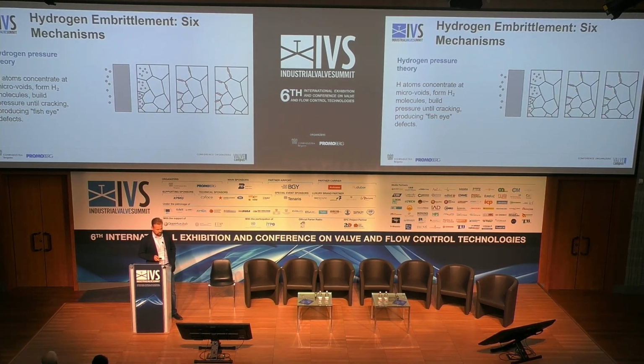So, going straight into it, the biggest problem that we have probably heard the most about is hydrogen embrittlement. Okay, so the sometimes reversible, sometimes irreversible loss of mechanical structure of metal. There are 6 different possible mechanisms. Some of them were actually observed, some of them are just theories, and the math is there, so it just works because the calculations are on point. One of the easiest and oldest theories is that the embrittlement might occur because of the high pressure of hydrogen.